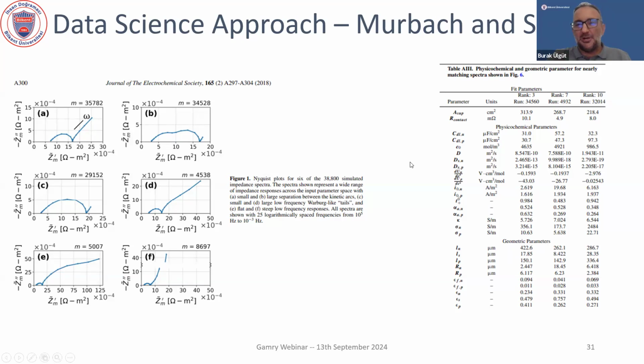And this can be very wild. For example, if I can attract your attention to this diffusion constant, which is the diffusion constant on the positive side, it can be -15 or -17. If I can attract your attention to this particular variable, which is an electric field, you can see it can go from -43 all the way down to -0.02. Here's another diffusion constant, -13, -19. So this can be very wild. So my idea was to use the temperature dependence and the nonlinearity in order to break this degeneracy.